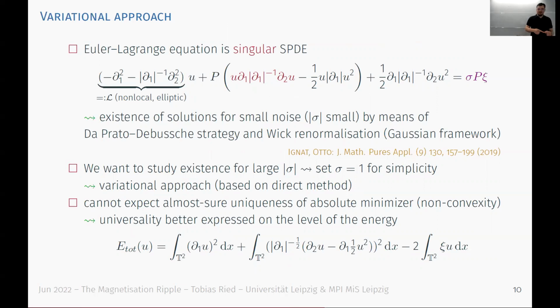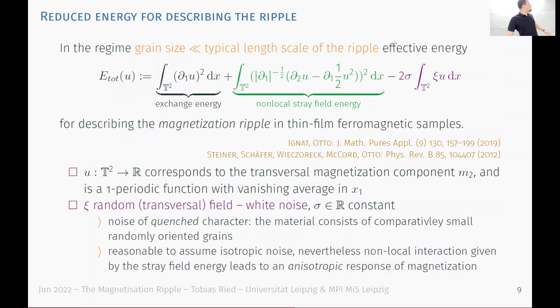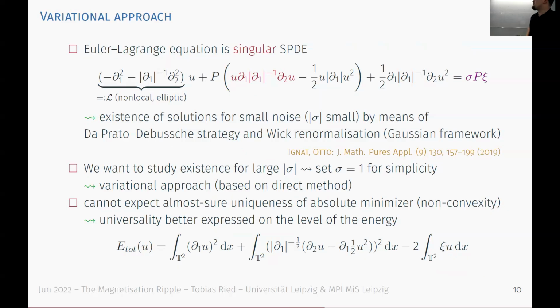Okay. So that also has to do with the way we treat the equation. It turns out that due to this thin film limit, you somehow get this negative half derivative of this Burgers term. Essentially what we're studying is really small oscillations around the 1-0 magnetization. So is it because of the thin film limit that it becomes singular? That gives us an anisotropy that we see in the equation, in the sense that it's a non-local operator, but the operator has an anisotropic scaling. It treats the D1 and the D2 direction somewhat differently.